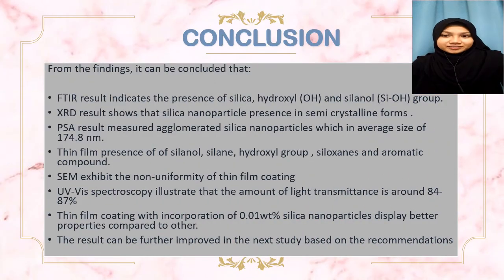Okay, as a conclusion, from the findings, it can be concluded that FTIR results indicate the presence of silanol and hydroxy group that will contribute to the hydrophilic properties. And XRD results show that the silica has a semi-crystalline form. And the PSA result measures the agglomerated silicon nanoparticle, which is on average 174.8 nanometer. For the thin film, the composition present consists of silanol, silane, hydroxy, siloxane, and aromatic compound.